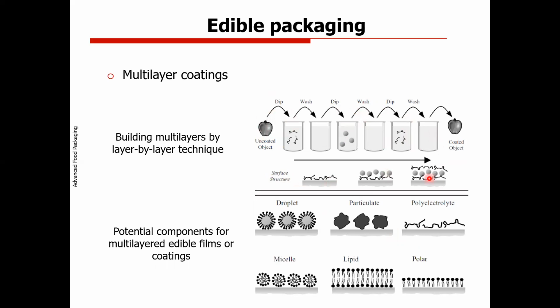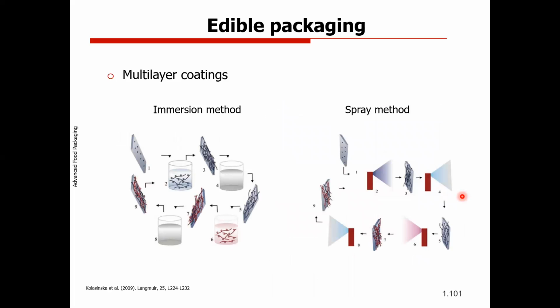And then you have this surface structure, built as a nano multi-layer. These are the kinds of components that you can use: polymers, particles, droplets that can be used for encapsulation. I have to show you with nanoparticles, lipids, and the polar system. So depending on the material that you are using, you can add different compounds to the surface to build this multi-layer. These multi-layer coatings can be applied by the immersion method, which is the most used because it's more affordable, or also by the spray method. We tested immersion a lot, but right now we are focused on the spray, because we believe that the spray method can be mostly used for industrial applications, and we can reduce the amount of material that is used, and with that save some money for the companies.